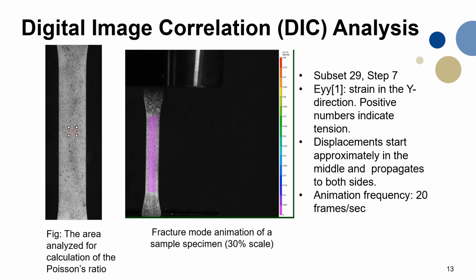As I play these videos, you can see the displacement starts approximately somewhere in the middle. As you see, the color changes here, and there is more deformation here, and it propagates to both sides, and eventually it will stop and has the highest stress concentration in this area. So this area has a high possibility of breaking.